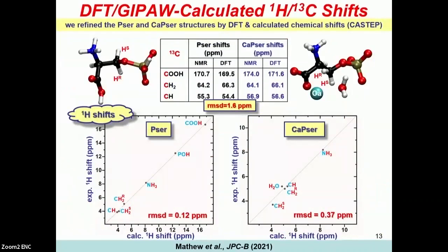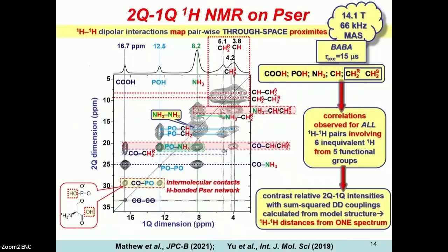So I will get over to the last part of my talk, which concerns a new NMR crystallography method. We took the XRD structures of phosphoserine and its calcium salt, and we refined them by DFT calculations in CASTEP. That resulted in overall good agreement in both the carbon-13 and proton chemical shifts. Now our method is not relying in any way on chemical shifts, but rather extracts either homonuclear or heteronuclear distances from dipolar recoupling NMR experiments. You only need one experiment, but it needs to be recorded using a very short dipolar recoupling time to establish through-space proximities.